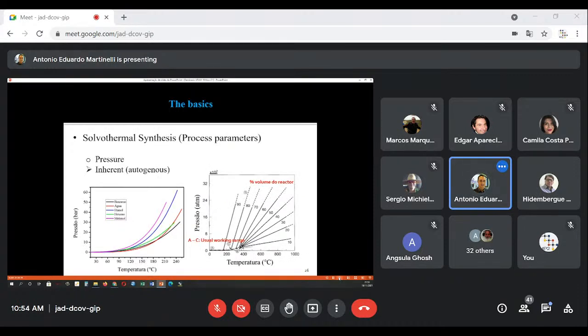Now for the pressure, the solvent has the function of conducting the thermal energy and also to increase the pressure during the process. Each solvent has its own relationship between temperature and pressure, as we see here in this picture. Pressure has no significant effect on crystal growth rate, but it influences other parameters such as mass transfer and solubility and therefore morphology. It is possible to vary the autogenous pressure, which is the inherent pressure of the process, just by varying the filling percentage of the reactor volume, or we can apply an external pressure, which is what we do in our reactor.